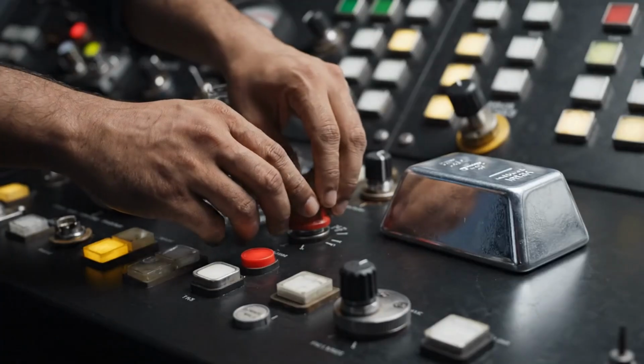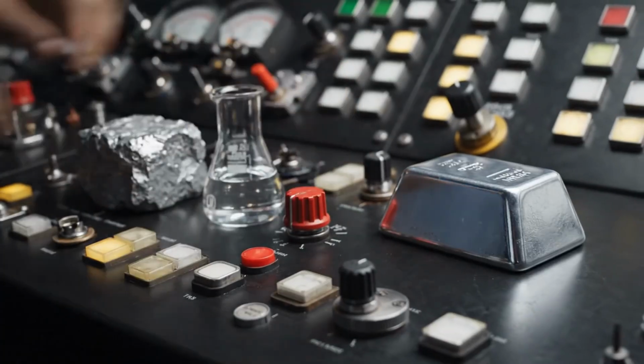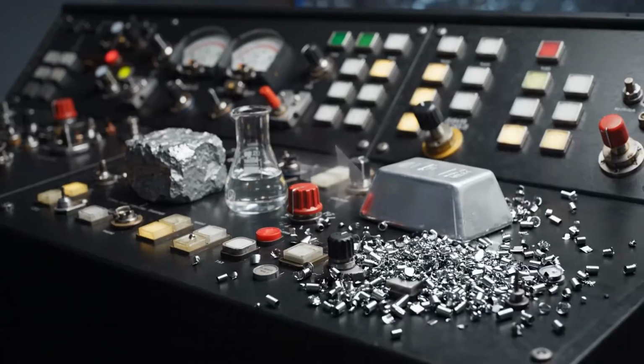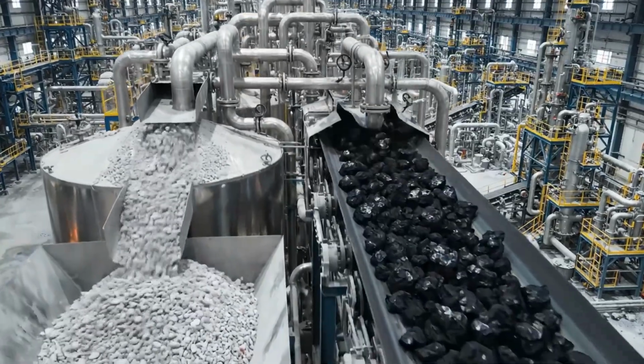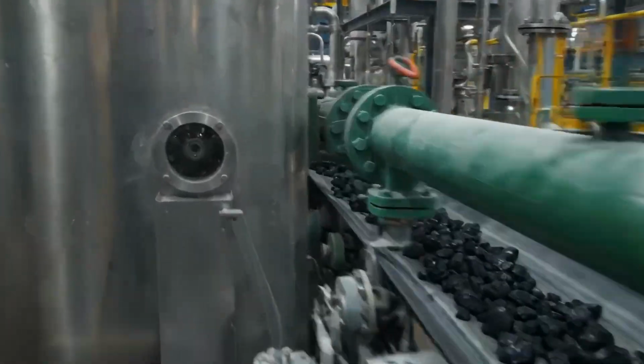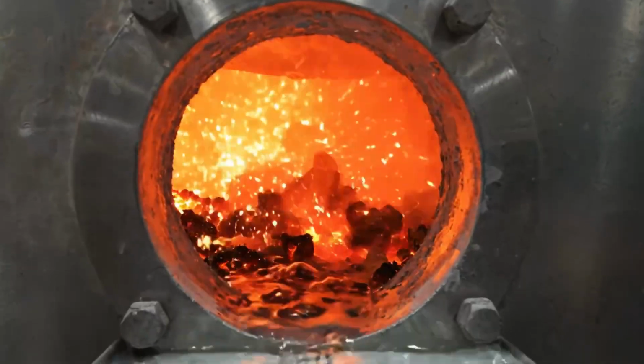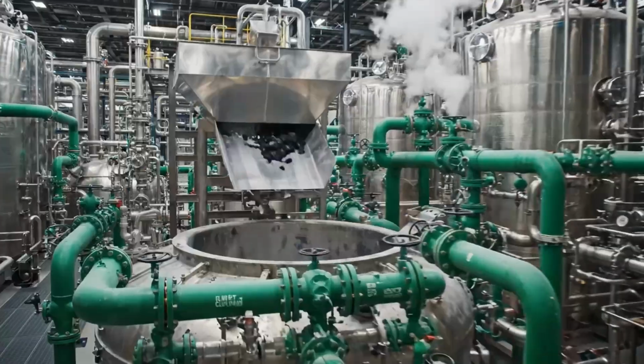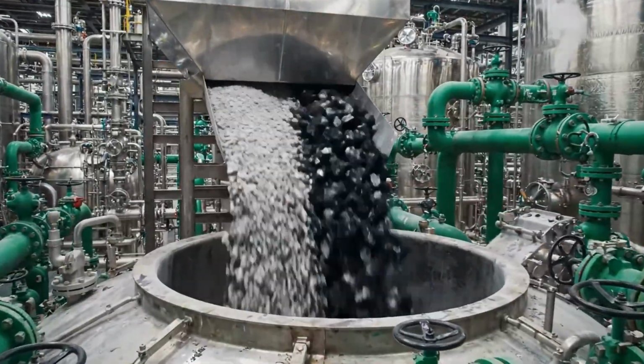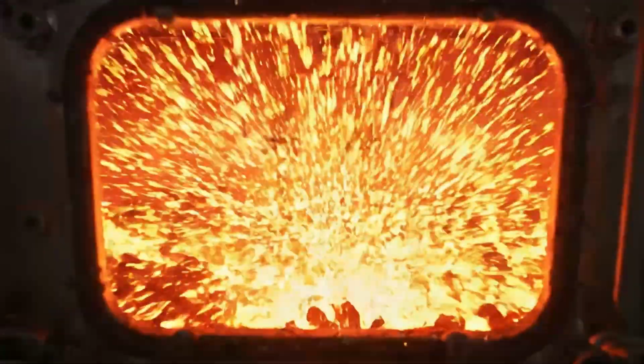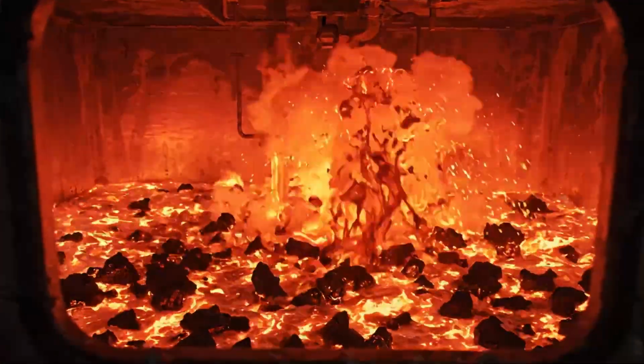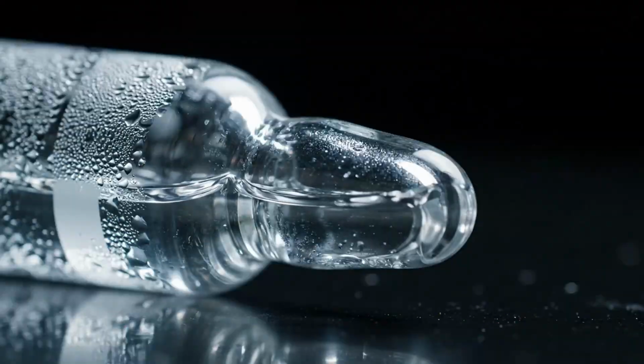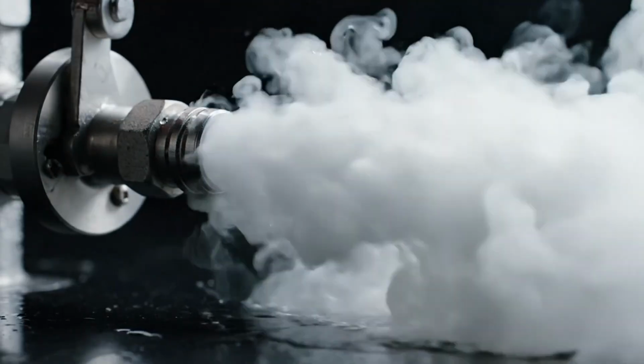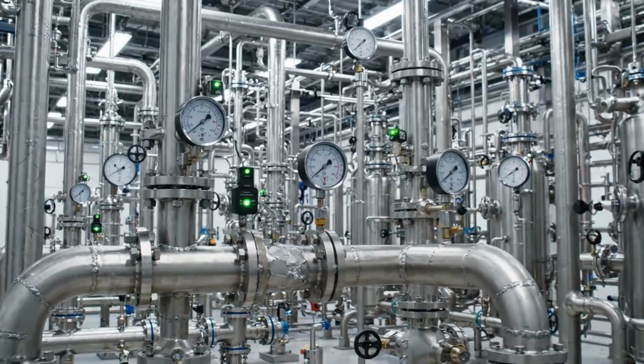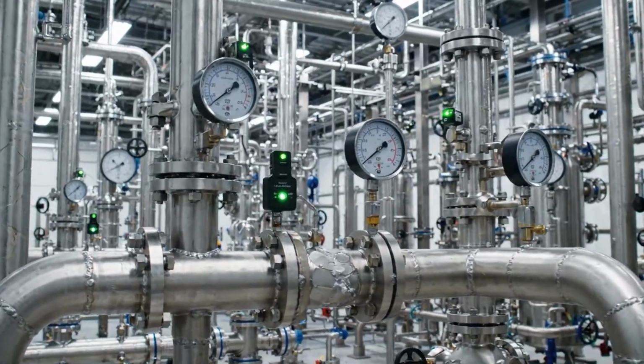Since titanium is strongly bonded to oxygen, titanium oxide is first converted into titanium tetrachloride, a chemical compound that can then be reduced with magnesium to release the metal. Rutile concentrate, synthetic rutile, or titanium-rich slag is fed into a chlorination reactor, along with carbon, usually in the form of coke, and chlorine gas. At elevated temperatures, the titanium dioxide reacts to form titanium tetrachloride, known as TiCl4.